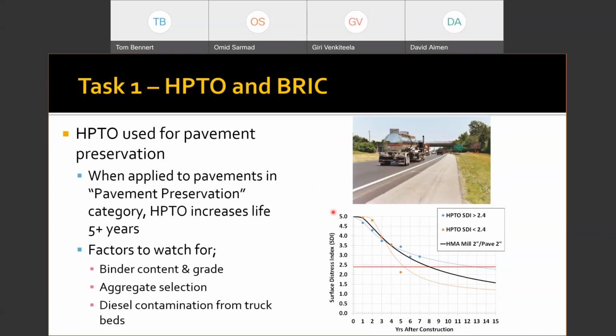And again, what we've done here is we've looked at what drives performance, looking at the factors to watch, such as the materials, things that we can recommend to inspectors while they're out on the job. But then also looking within the pavement management system, we can see that this material actually increases the pavement life over 5 years greater than our typical hot mix asphalt overlays, our typical mill and pave process. So those 5 additional years, now you can go ahead and allocate money to someplace else.